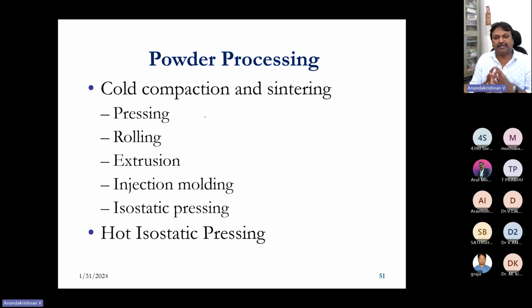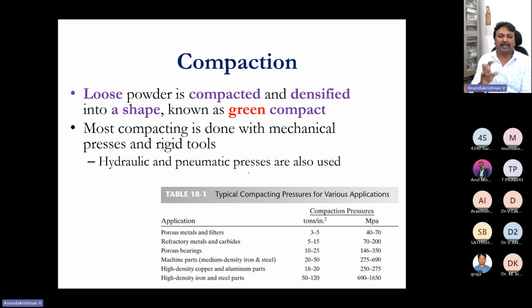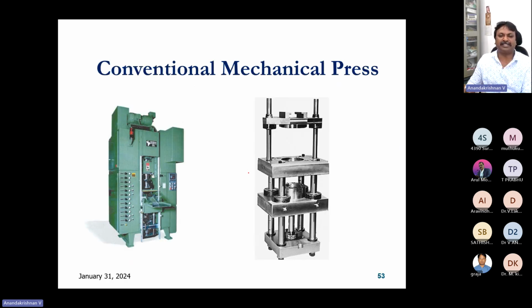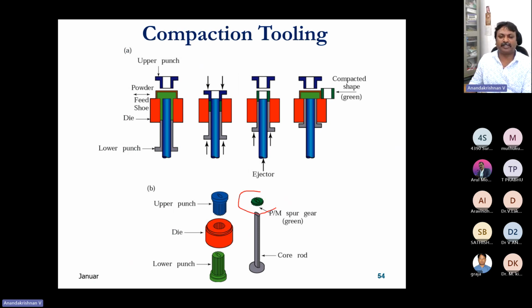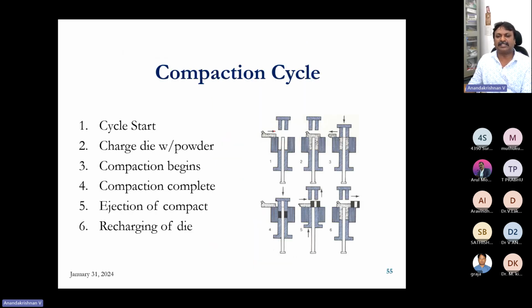After the powders are mixed, in the conventional method they press, roll, or extrude, or they use injection molding or isostatic or hot isostatic pressing. Also some glimpses. So the loose powders now have pressure applied to create a component in the powder metallurgy technique, either by using a mechanical press. For example, if you want to create a small spur gear with a helical hole inside, there will be an upper punch, a lower punch, and a die inside which you fill the powder like this. The upper punch moves down and the lower punch moves up, and then you can create a consolidation of the powder inside, and then it is ejected. I'll show the cycle: powder filling, compaction starts, compaction completed, component ejected, and then it is taken out.